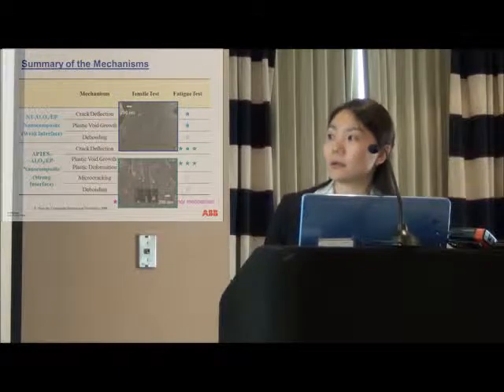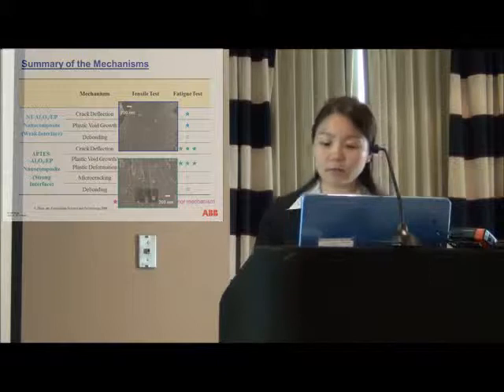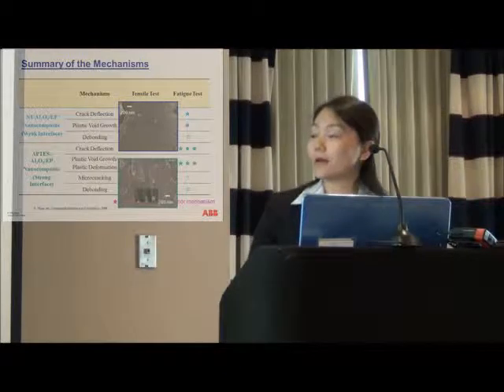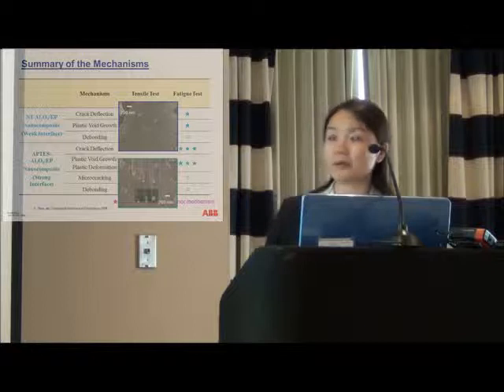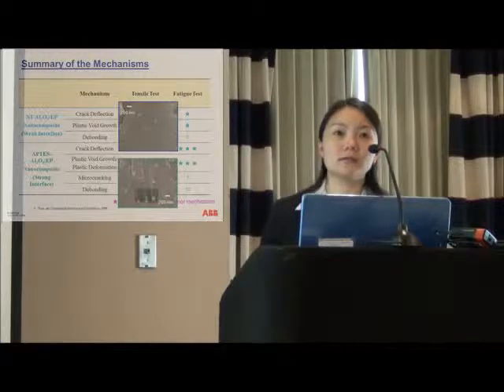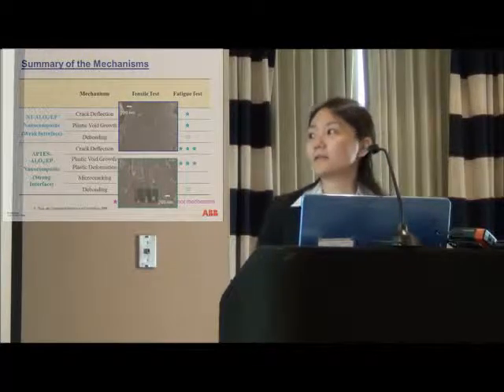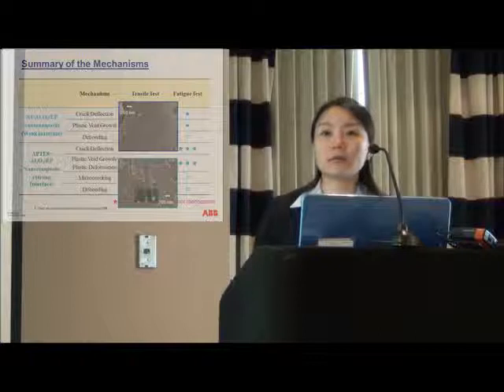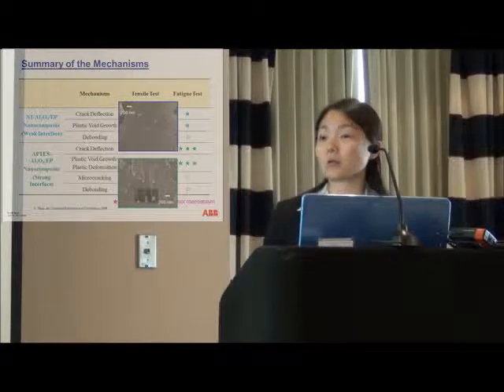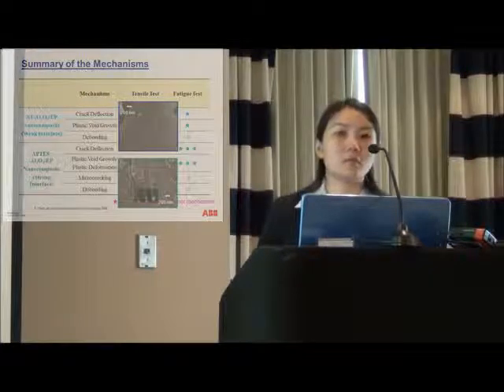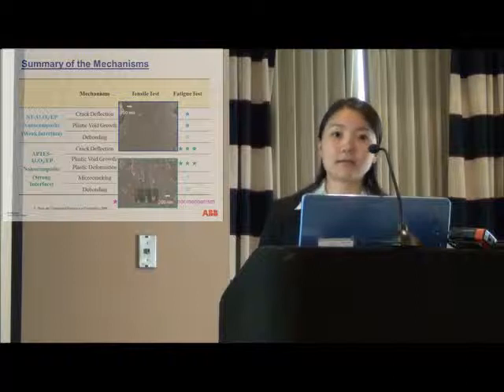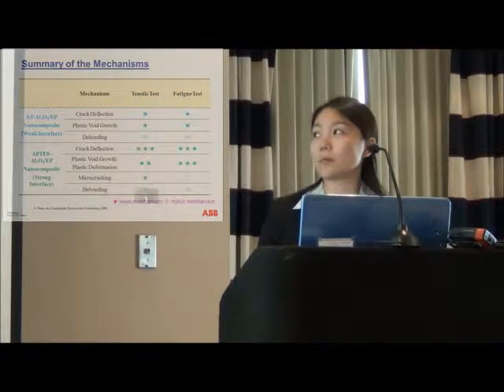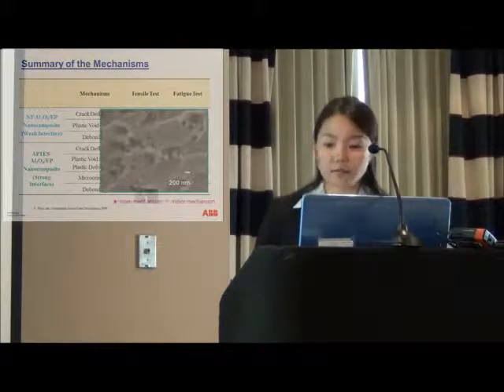But when you have a much stronger interface, in the green one, when the crack approaches the particles, since you have a stronger interface, the crack will go around the particles and in between the matrix, which increases the overall crack length, since it absorbs more energy during crack deflection.